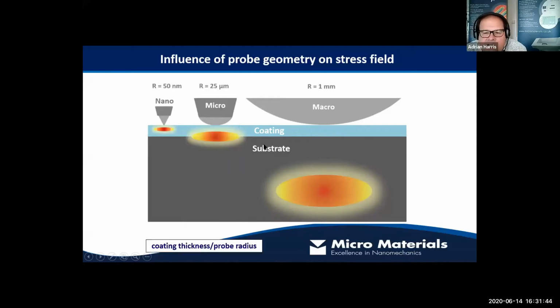But by using an intermediate load range in the form of micro impact testing, we can also use an intermediate tip size. So typically we use something in the region of 10 to 25 micron radius tips, and that can allow us to put the stress maximum at a depth which is closer towards the region we're interested in. Okay, so you can very easily change the probes to match what you're trying to achieve.